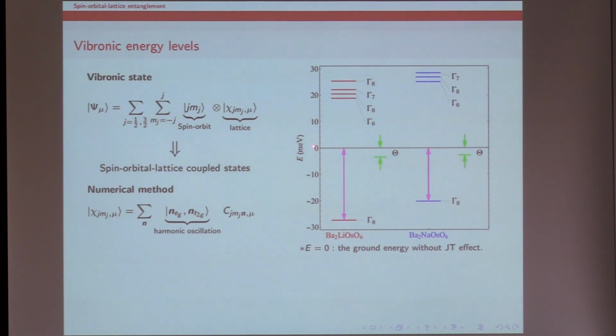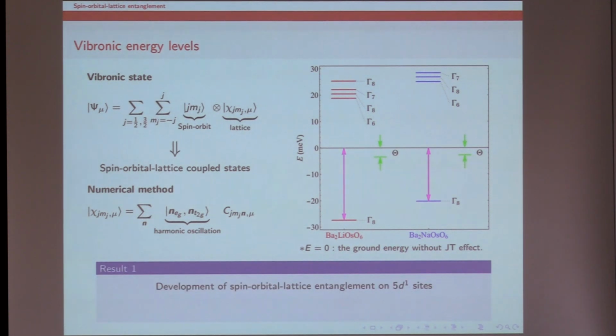This 0 is the energy without the Jahn-Teller effect, and this line shows the vibronic energy levels. These two are osmium, and both show there is a relatively large stabilization by dynamical Jahn-Teller effect. And we compared this energy, which is much larger than the inter-site interaction measured by Curie-Weiss constant. So based on this, we concluded that there is a spin orbital lattice entanglement on 5d1 metal site. And this explains why in X-ray data there is no clear Jahn-Teller deformation.